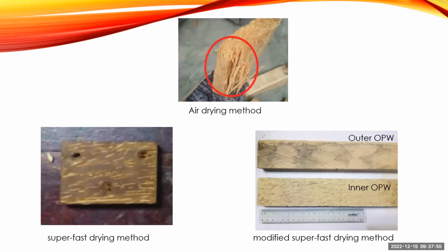The visual appearance of the oil palm lumber dried with the super fast drying and modified super fast drying methods are shown in the figures. From the figures, we can see that no visible drying defect was detected during the drying process for both inner and outer oil palm lumber.